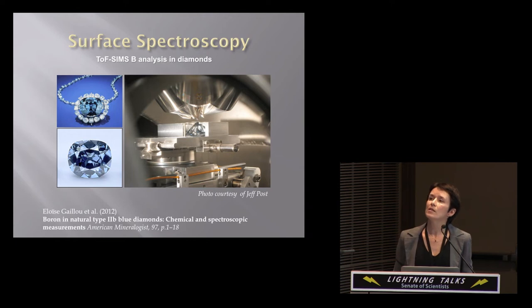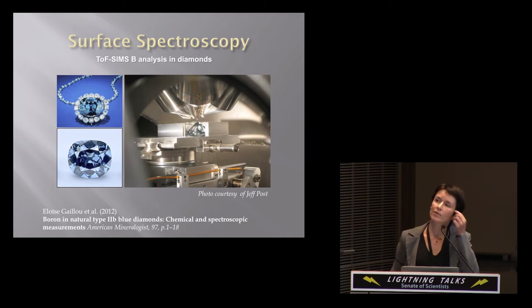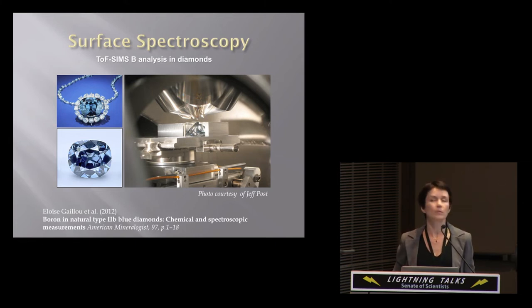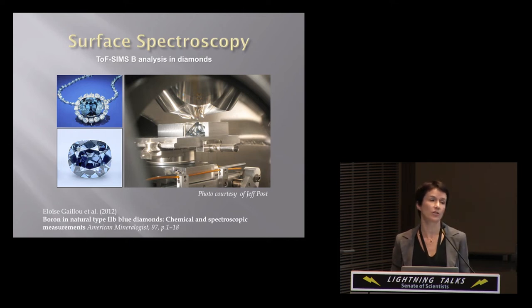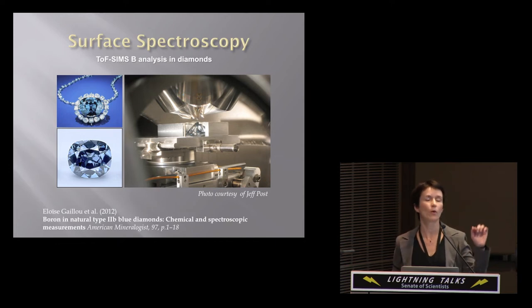Here's a snapshot of work done by Eloise Gailou, Jeff Post, and others in our department. They've done wonderful work analyzing boron in blue diamonds. This is our own Hope Diamond — mounted top left, unmounted bottom left, and mounted again in the machine top right. They found that the boron content in the diamonds is actually a mere half of a ppm concentration — incredibly low — and they were able to measure it. One reason they could perform such analysis on the Hope Diamond is that the technique is virtually non-destructive; you only disturb the very, very top layer.